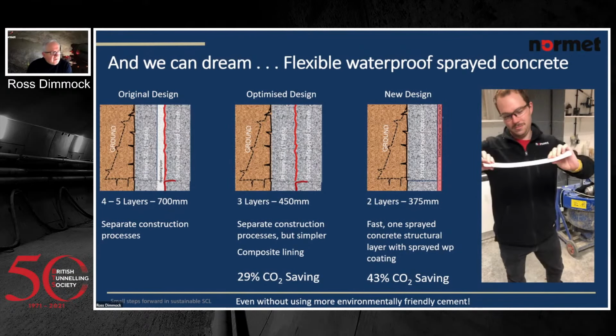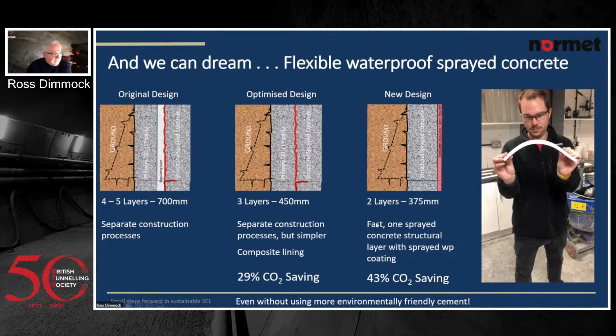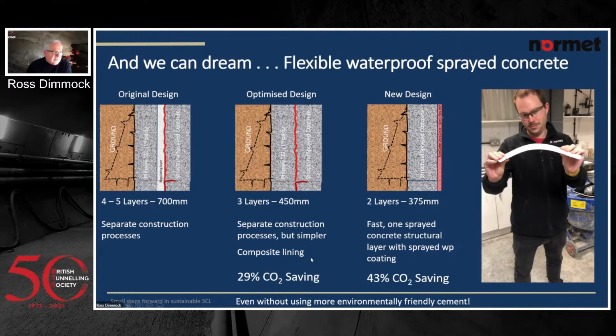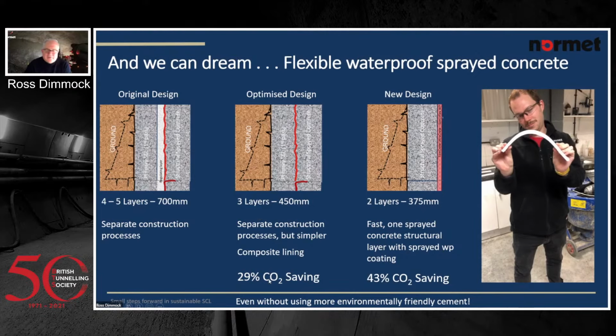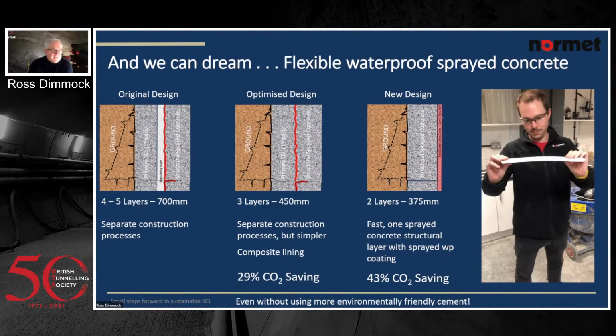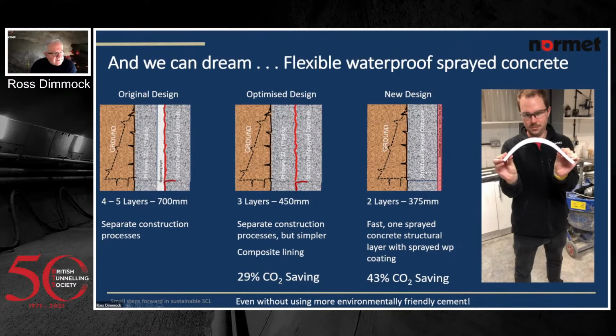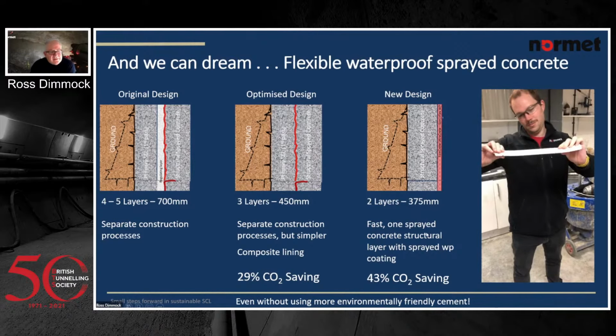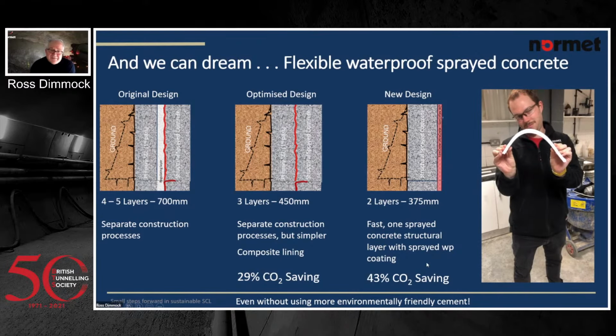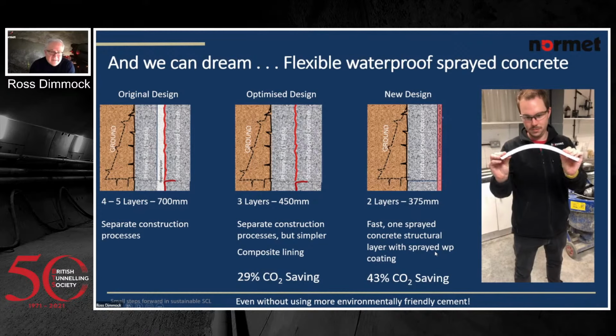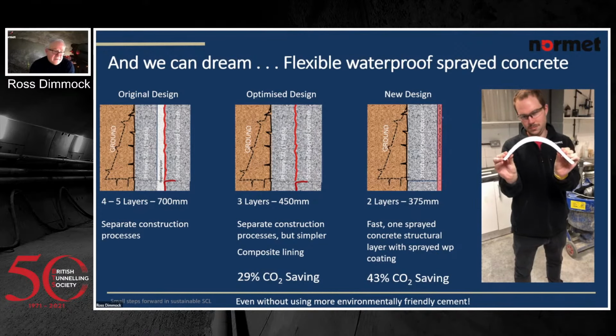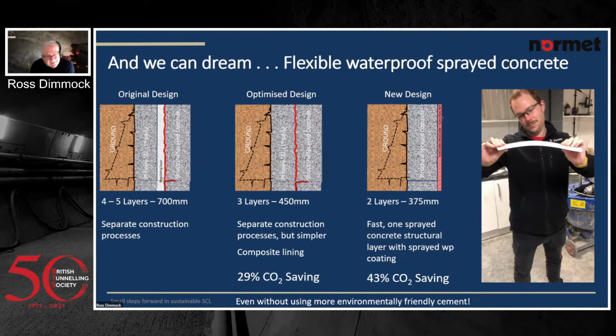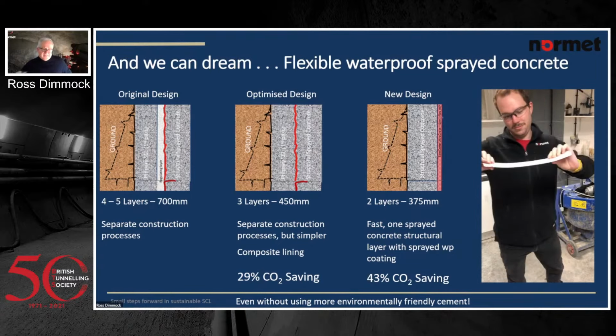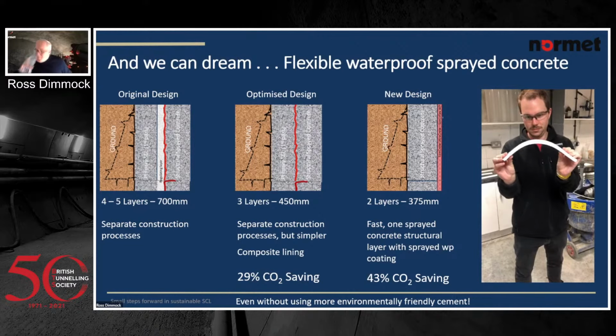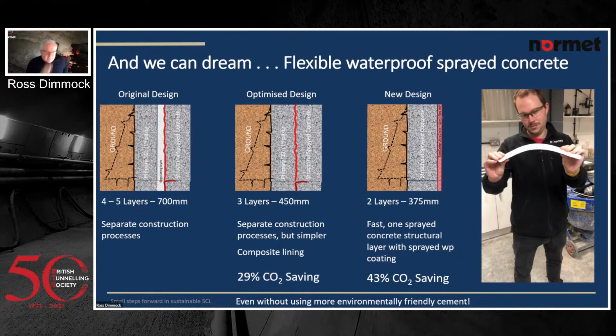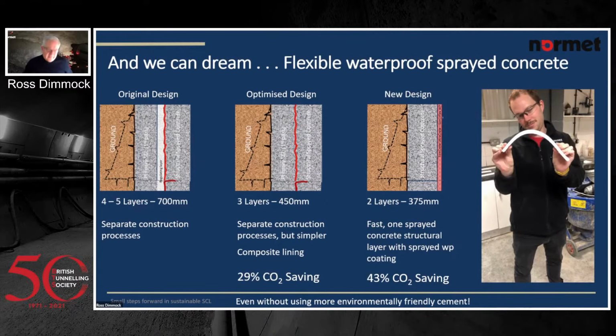On those options that we looked at with Sert Consulting, our initial studies looked at a sort of optimized design. We could get around 30% carbon saving with that. With this much simplified approach, we're almost halving the lining thickness and getting around 43% saving in carbon. And that's without even changing the cement type. So if we were to change the cement as well, we could be over 50 to 60%. They're wild ideas, but that's what we're working on, and hopefully we can get that to work.